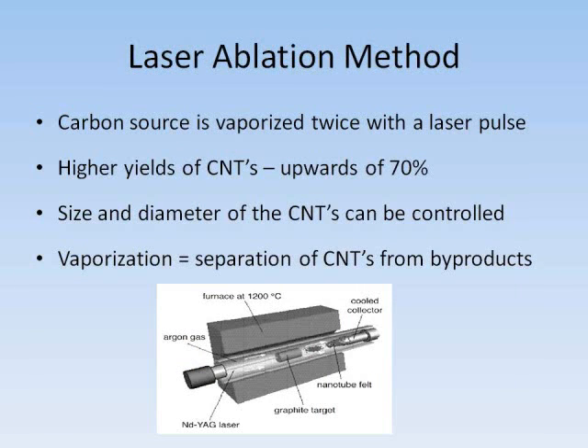The next method is the laser ablation method. This method gives a higher yield than the arc discharge method, upwards of 70% by mass of the products. In this method, a graphite sample is vaporized by radiation from a laser, usually an infrared laser. As carbon particles are broken apart, atoms form the nanotubes on the cooler surfaces of the reaction chamber. This process utilizes a catalyst — usually cobalt and nickel — to drive the reaction forward at a quicker rate, hence the higher yield. The first laser pulse vaporizes the graphite sample, producing synthesized carbon nanotubes among soot and debris.